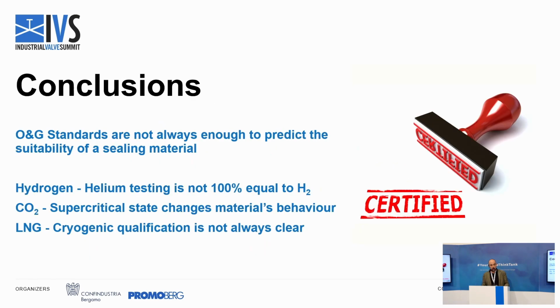So in conclusion, oil and gas standards are important, of course, but are not always enough to predict the suitability of a sealing material, especially when it comes to these sectors. The hydrogen sector, we can have high temperature, high pressure, 100% hydrogen. Helium testing is not always 100% comparable to hydrogen. We can't be sure that a helium test gives the same results as hydrogen. We saw it for the RGD, for example. We saw it also for the compression packings with the dynamic conditions.